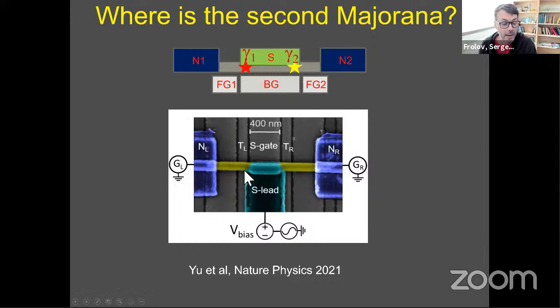So almost the same as before, just really here's a nanowire and a superconductor and a tunnel contact on the left, and there's just another one on the right. So there's two of them, left one and the right one. And what you can do is, for example, apply bias to the middle and send current to the left and right, and look at the simultaneous correlations of your signal on the left and on the right. So if you have two Majoranas, like gamma 1 and gamma 2 here in the picture, then you should see some correlated evidence of that.